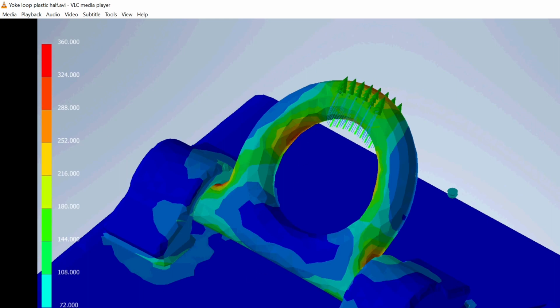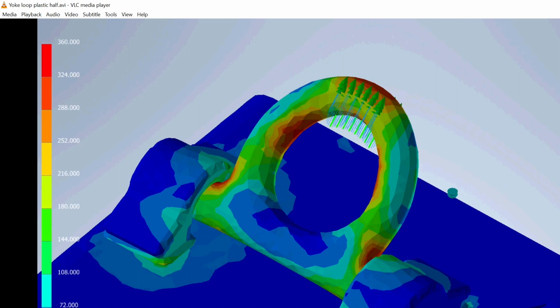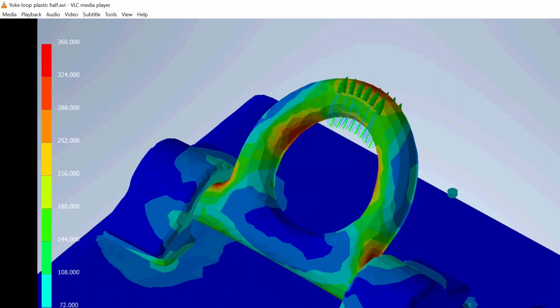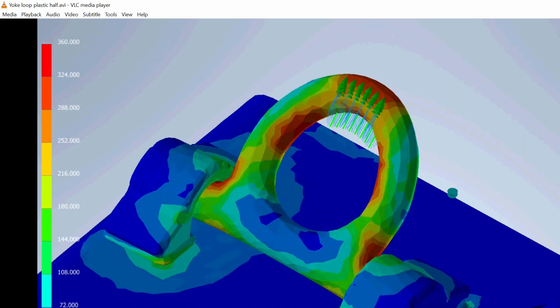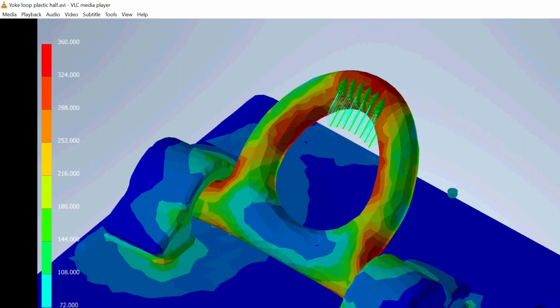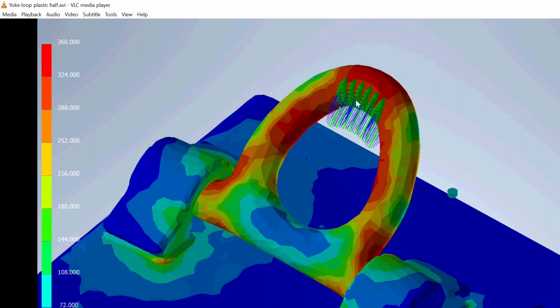You just avoid concentrations of stresses and maybe refine the elements in those areas, and that's it. But you end up with pretty much half of the total holding capacity, which is of course safe, but perhaps not always the most efficient. Then if you have something that needs to hold the load only once, or twice or a few hundred times in exactly the same direction, plastic strength with a coefficient reducing the strength could be an option. And if there's cyclic loads on this, then you have to make sure that they're not that many.